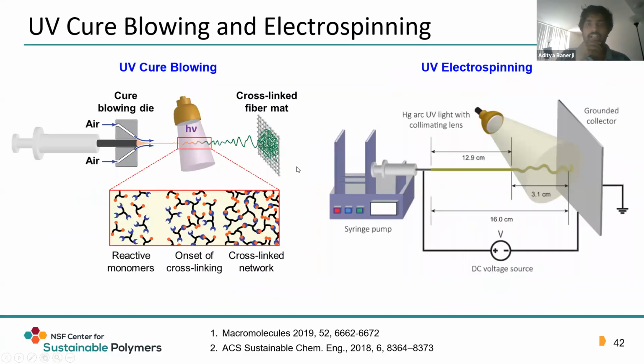Moving on, current research in our group has focused on modifying these melt blowing and electrospinning methods through what we call UV cure blowing and UV electrospinning. What sets these apart from conventional processes is that instead of a polymer melt or polymer solution, we use a reactive monomer mixture, for example comprising thiol-acrylate monomers, thiol-allyl ether, or other thiol-ene monomers, which are extruded through a die and then drawn by air jets or electric field in both cases.